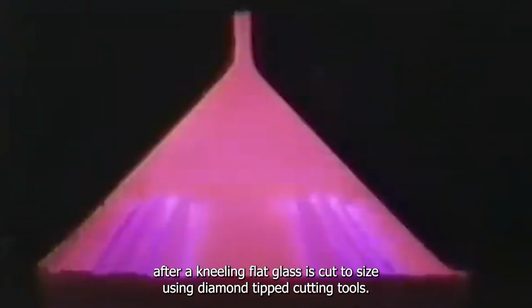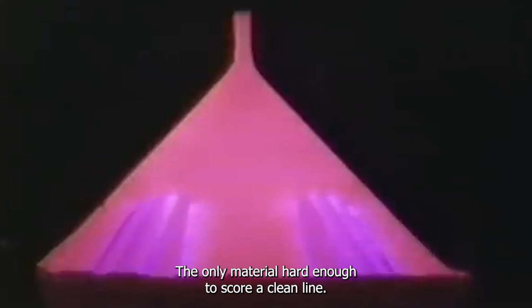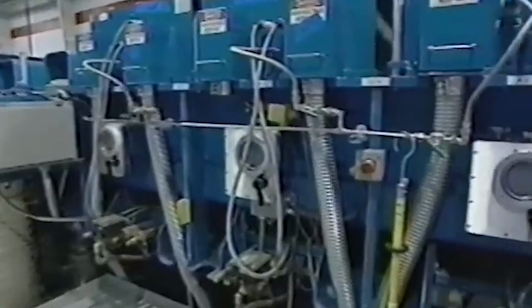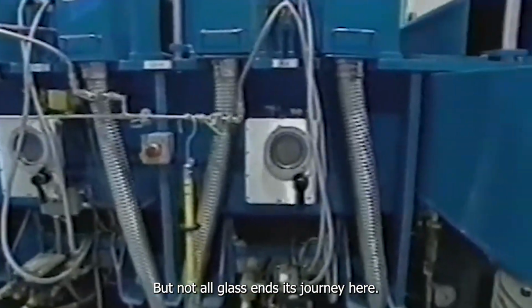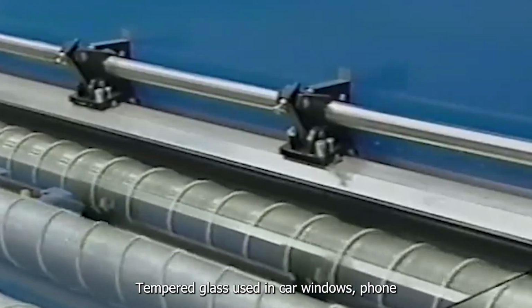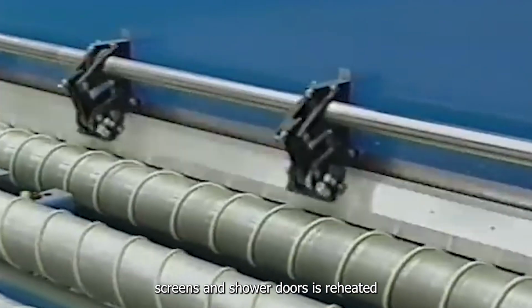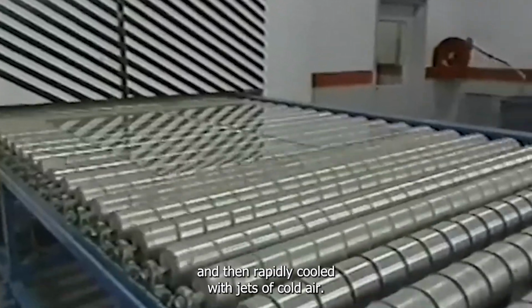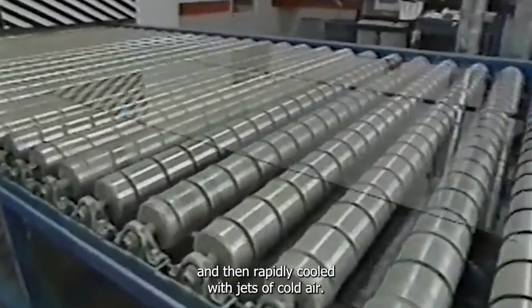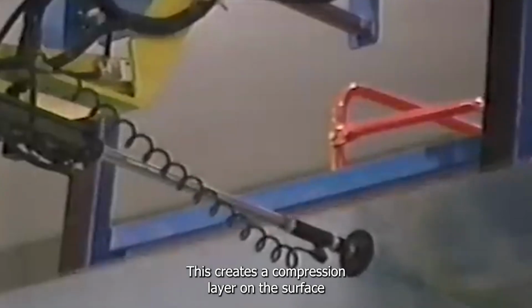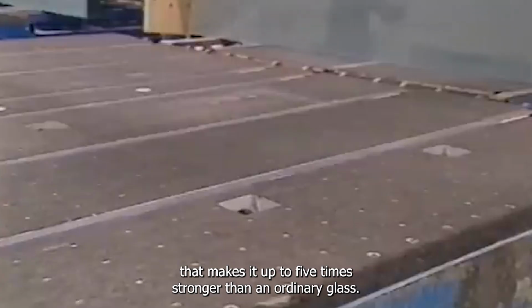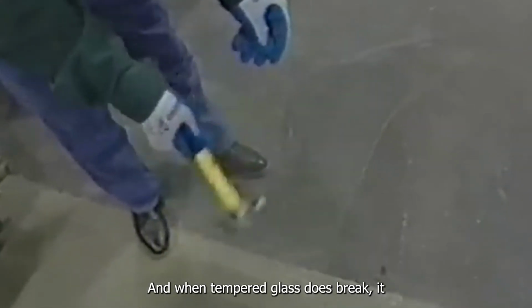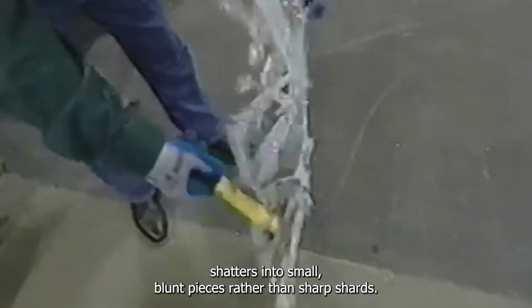After annealing, flat glass is cut to size using diamond-tipped cutting tools, the only material hard enough to score a clean line. But not all glass ends its journey here. Tempered glass, used in car windows, phone screens, and shower doors, is reheated and then rapidly cooled with jets of cold air. This creates a compression layer on the surface that makes it up to 5 times stronger than ordinary glass. And when tempered glass does break, it shatters into small, blunt pieces rather than sharp shards.